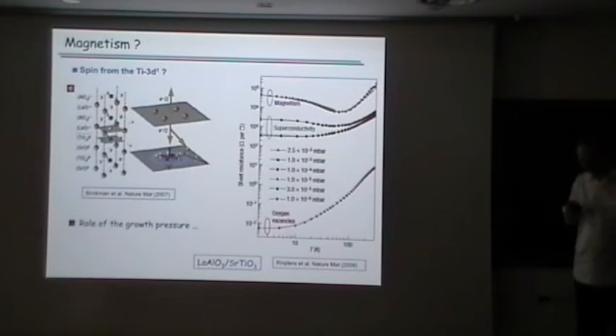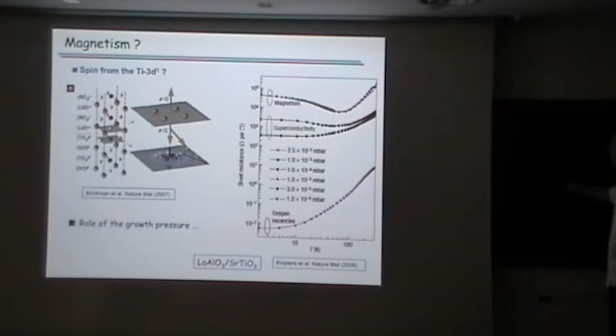Okay. First of all, the raw data here are from Brinkman. But these regimes here are from this paper from Reyren. This is a comment saying that maybe we have a different regime. The belief is that in this case, you have oxygen vacancies probably in the bulk.